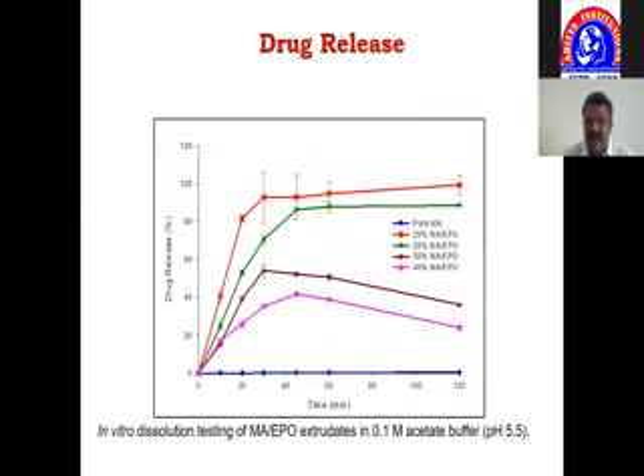Again, we see the drug dissolution profile. You see mefenamic acid pure drug at the bottom. It is almost close to zero, but as you start converting into a solid dispersion, the lowest drug loading, which is 20%, gives you the highest drug release. The rate as well as the extent are both high.